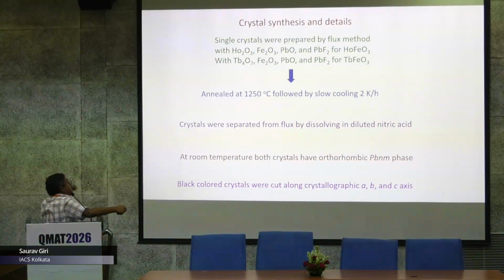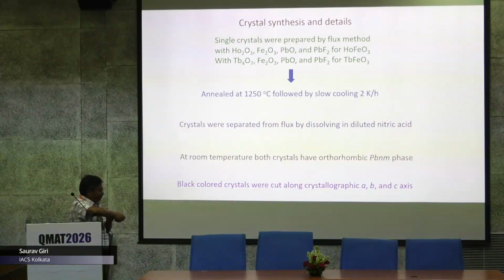We studied single crystals. I am not going into the crystal preparation. However, we oriented the crystal. At room temperature, this has a Pbnm phase, which is orthorhombic. So we cut along the a axis, b axis, and c axis for our measurements.